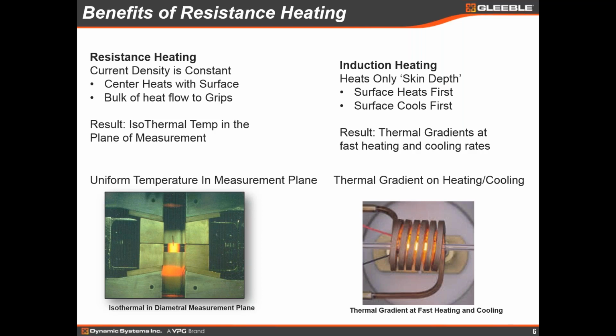Now, if we compare that to induction heating, as we know, it does have a skin depth, so it does heat a little bit into the surface of the sample, but the skin depth, depending on frequency, is usually quite small. So in essence, induction heating is very similar to furnace heating in that we are really only heating the outside of the sample, and we have to let that heat soak into the center of the sample. Now, if I'm trying to do a dilatometric experiment at 1 degree C per second, 5 degrees C per second, maybe even 10 degrees C per second, it's not really critical because I have plenty of time for that heat to soak into the sample, and the thermal gradient I'm developing is probably very small.